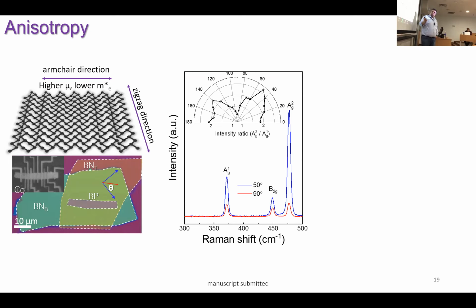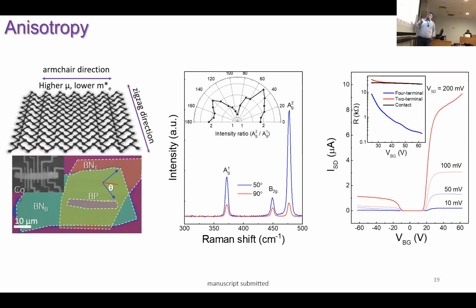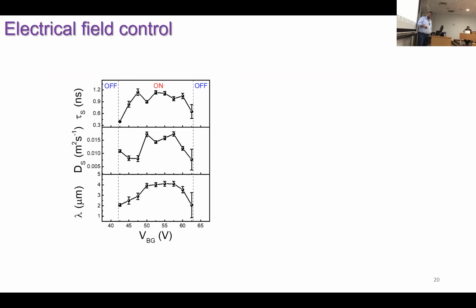And here we chose some black phosphorus samples, and we did a quite detailed Raman study to understand the crystal direction, so that we know which direction is armchair and which one is along the zigzag direction. I will not go into detail, but basically around 50 degrees was the one where we started to hit the armchair direction, and we prepared the contacts accordingly. And this is just the basic charge transport characterization of this device. We were seeing mobilities around 4,000 at low temperature, which was a quite good sample to start with.